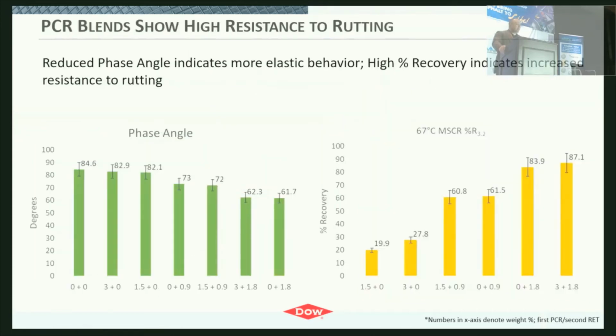Phase angle, you see that here on the left, the mixed samples were about the average versus the PCR only, unmodified, or the RET only. On the right, we have 67C MSCR percent recovery. And again, it's about the average between the RET only and the PCR only. And so here you can see in the middle, that's the combination.